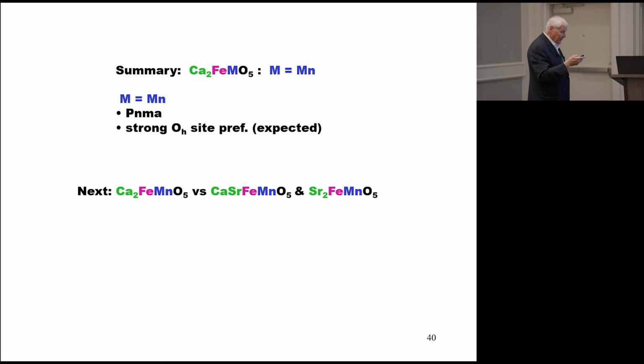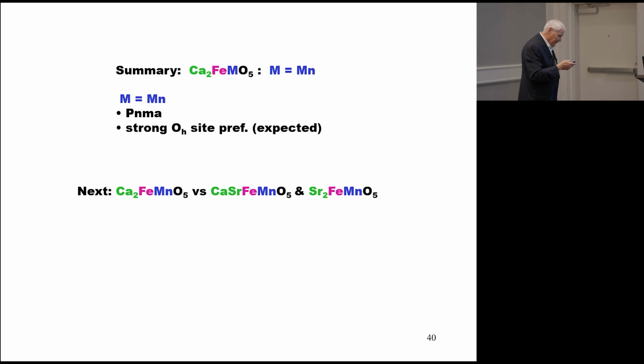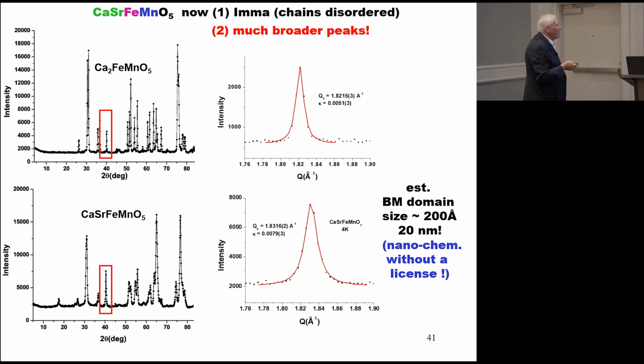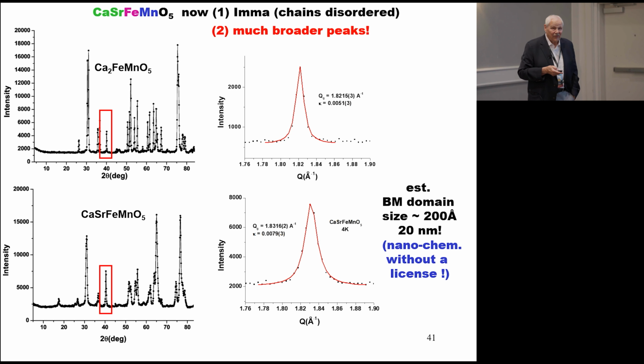So we get the strong site preference energy that we expect, the strong Oh site occupation for manganese. Now we're going to compare what we get when we substitute 1 strontium for calcium and 2 strontiums for calcium. Okay. Well, 1 strontium for calcium, we get a change in space group symmetry.